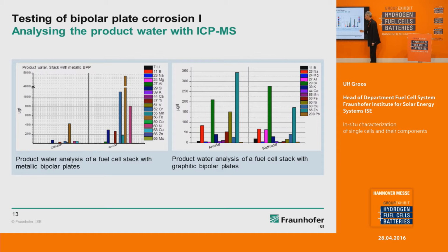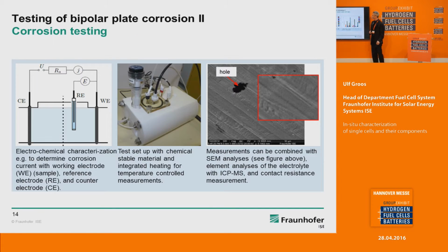In this case, we used a graphitic stack, and again we collected the product water, and again we found some amount of zinc in the product water, and also silicon. So this can allow you some optimization of your system components. If you find some harmful elements in the product water, you should think of where they are coming from and what you can do about it, so that you have a long-term stable stack and fuel cell system.